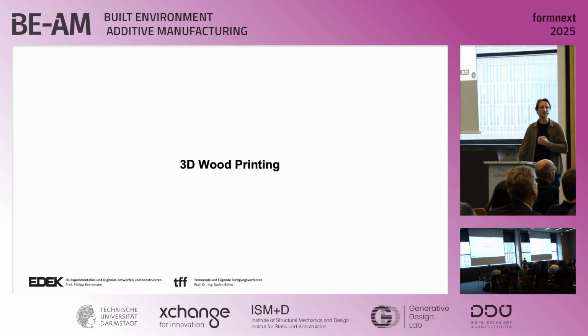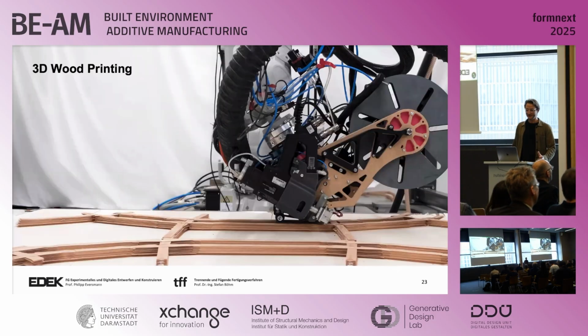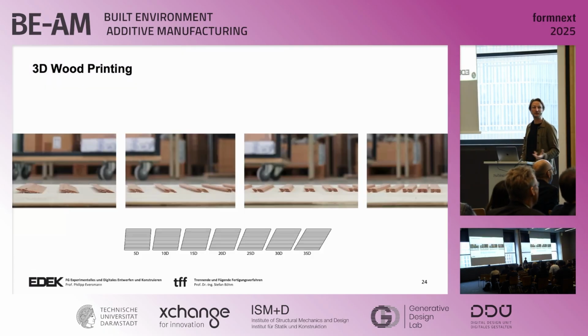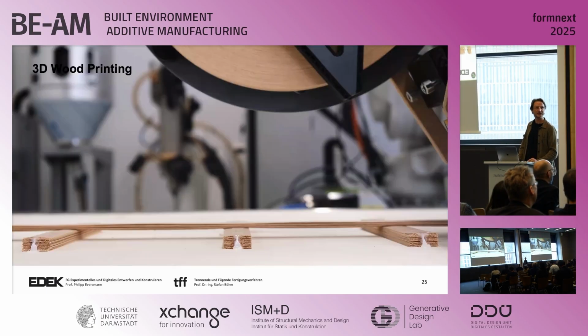So we're also looking at the application of this in a horizontal layer-by-layer approach, so more traditional 3D printing. When you do that, that results in completely different requirements for the whole process, because there, for example, we can't apply this tension, compression, or so on. So we have used also different tools and fabrication processes for that. And also for the layup, you have geometric requirements. And we have developed tools for that through a huge amount of iterations. It's possible, you see here, to print overhangs around 35 degrees. We can even print bridges into the air, laminate that into the air.